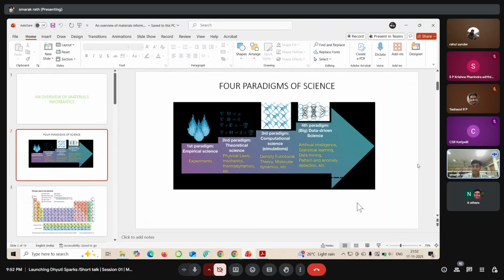That is the thumb rule with which you can predict what kind of grain size the material will have. Let's say there is a ceramic material which you synthesize by annealing at 800 degrees Celsius, and there is another which you synthesize by annealing at 1500 degrees Celsius. The one which you are annealing at 1500 degrees Celsius will have a much higher grain size. And I believe there are also efforts going on towards building single grain materials as well, right? Be it metallic or even non-metallic compounds.